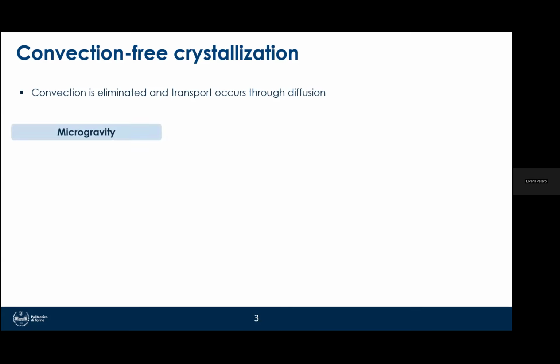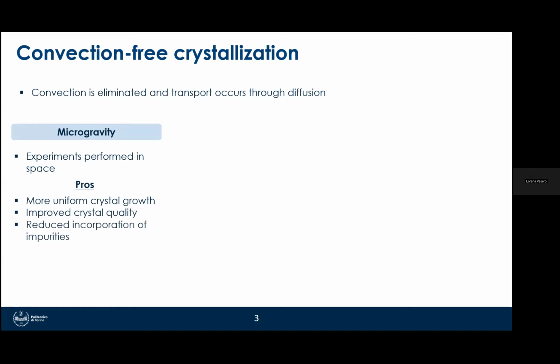Particularly, this can be obtained through different approaches. The ideal one is microgravity, where experiments are performed in space, and this can lead to the avoiding of convection, improved crystal growth, a more uniform crystal structure, and much improved crystal quality, since you can reduce the incorporation of impurities during crystal growth. But this method is really costly, and it is logistically complex.